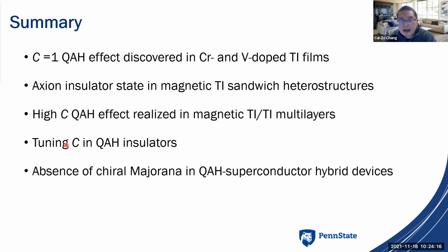And based on this kind of quantum anomalous Hall insulators, we fabricated the quantum anomalous Hall and superconductor hybrid device. We found that the half quantized plateau in transport is unlikely induced by the formation of chiral Majorana excitations. With that, thank you.